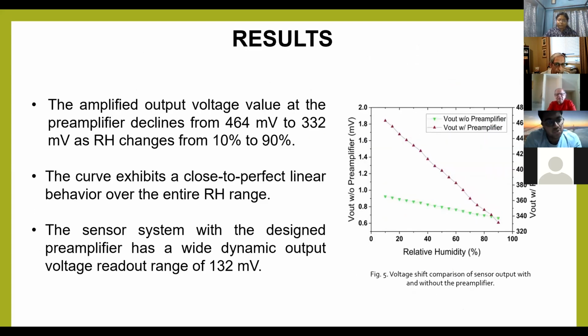Now, the assembled humidity sensor is placed in an AH202 sealed high or low temperature humidity test chamber to expose it to different levels of relative humidity to analyze the sensor performance in the presence of a preamplifier and without it. It can be observed that the amplified output voltage at the preamplifier decreases from 464 millivolt to 332 millivolt as relative humidity changes from 10% to 90% with an increment of 5% relative humidity during each measurement. The curve exhibits a close to perfect linear behavior over the entire RH range. It is important to note that the designed gas sensor system, along with the preamplifier, has a wide dynamic output voltage range of 132 millivolt, which helps the sensor to overcome its drift and make it less error prone.